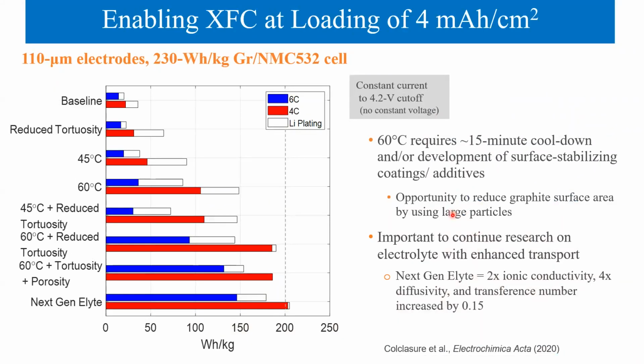Similar results can be realized for 4 milliamp hour per centimeter squared and non-conventional electrodes, but the operating temperature must reach 60 degrees Celsius. 60 degrees Celsius would require development of suitable coatings and electrolyte additives. Again, it's important to continue research on electrolyte with enhanced transport. 2 times ionic conductivity, 4 times diffusivity, and a transference number increase of 0.15 is ideal.